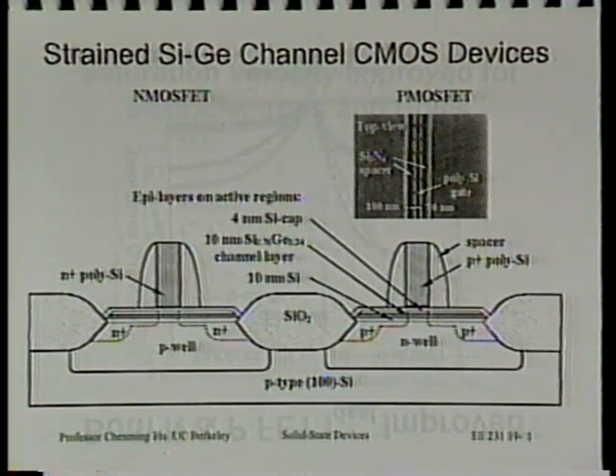Do you use the thermal oxide or do you use the LPCVD? We use the thermal oxide. Thermal oxide, so the top silicon cap is totally... Unfortunately, not totally removed. We actually would have liked to have less left. It depends on how much silicon you put down to begin with and how much oxide you grow. As you know, today we don't need a lot of oxide, right? Say 20 angstrom of oxide, which means only 10 angstrom of silicon is consumed. So for high performance transistors, we're not going to consume a lot of silicon, all right?